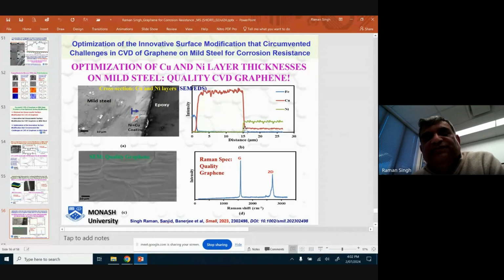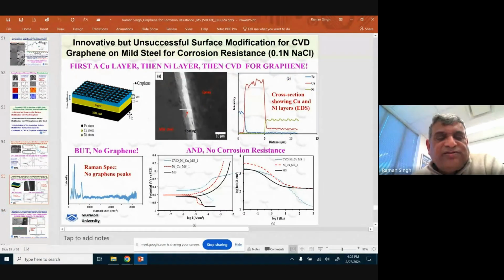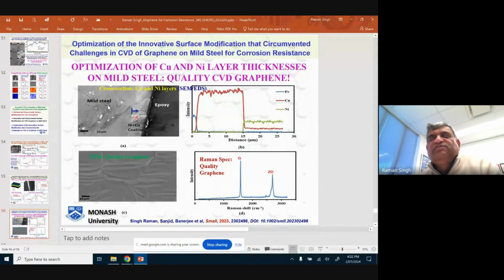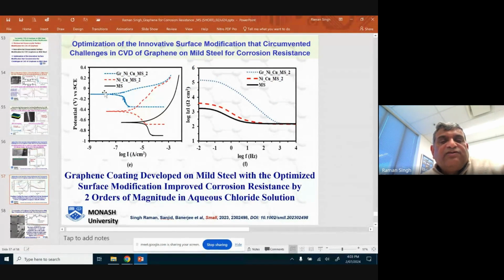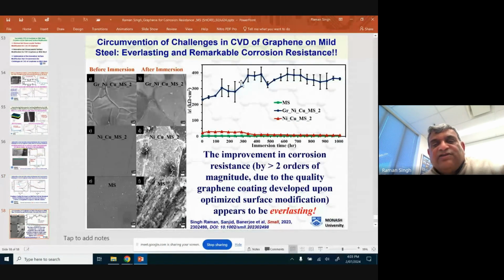We deposited a 15 micron thick copper layer, and then we deposited nickel on top of that, as I showed you here, 15 micron of this and then another 13 to 15 micron of nickel. And then we subjected it to CVD, and we developed a beautiful graphene layer. Very good layer, not much defect. The G peak is much taller compared to the 2D peak, so it is multi-layer graphene, and that multi-layer graphene gave very good corrosion resistance, as you can see here.